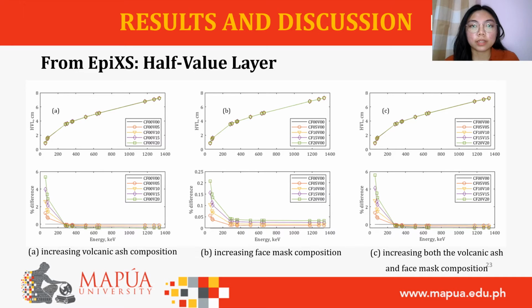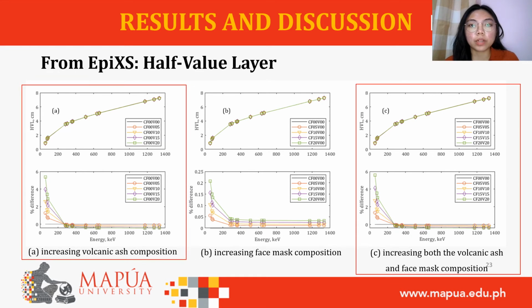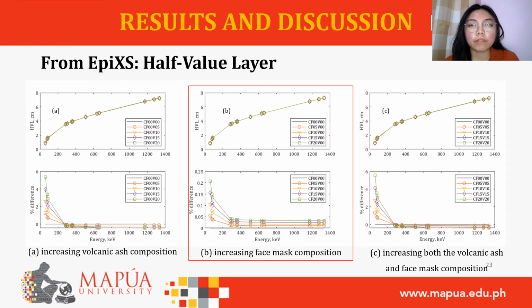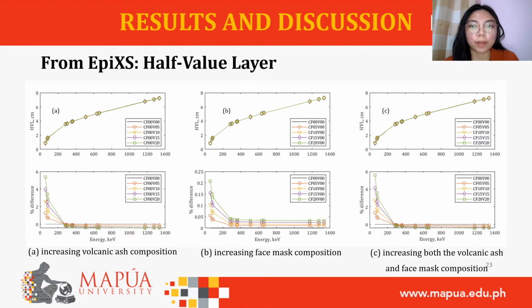Next is the HVL. Since HVL is inversely proportional to MAC, lower values of HVL are desired for photon shielding applications. As previously explained, cases 1 and 3 depict similar graphs as volcanic ash replacement is more prevalent in volume compared to the face masks. This means that adding face masks to the concrete mix has a negligible effect on the HVL. This result denotes that increasing the face mask composition in the concrete does not significantly affect the photon shielding capacity of the material, while the mechanical properties are improved in terms of compressive and tensile strength.